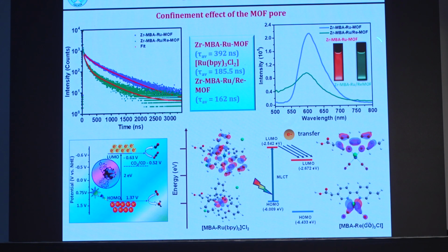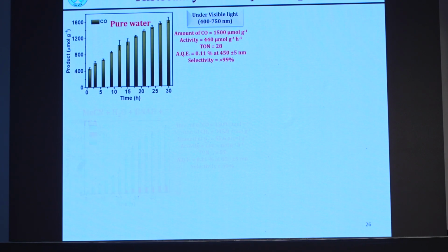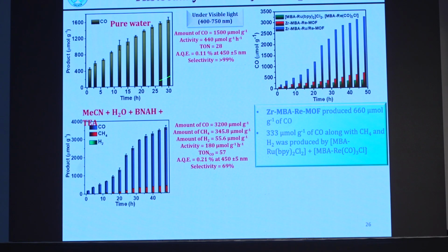Now, when you put the rhenium or the manganese, the emission decreases, and the lifetime also, suggesting there is a probability of electron transfer. This is the band structure, which is very important, that if you have the 0.63, it will connect this one. So now from the DFT, it is suggesting that the LUMO of this MLCT can go from the metal center to the bipyridine and goes to the rhenium bipyridine. So it does the catalysis, fine. Next, we have done the catalysis in pure water medium. CO is produced, a 2 electron process, with high selectivity, around 100%.